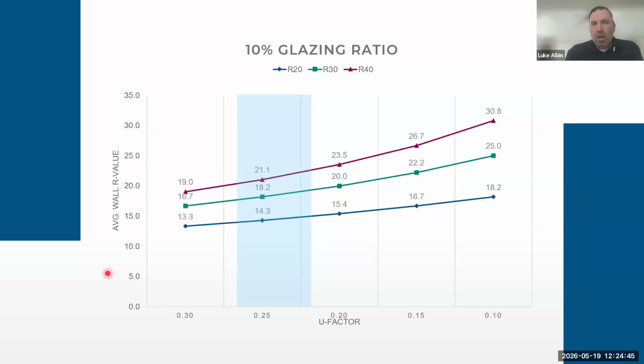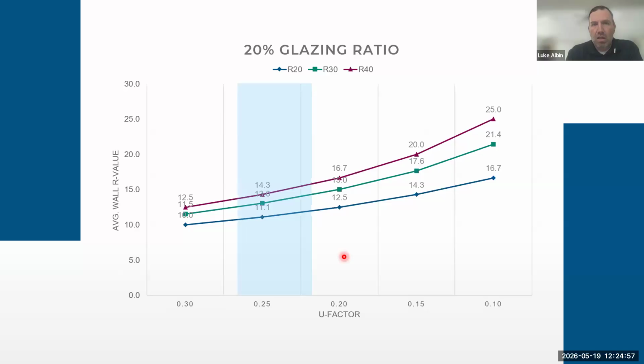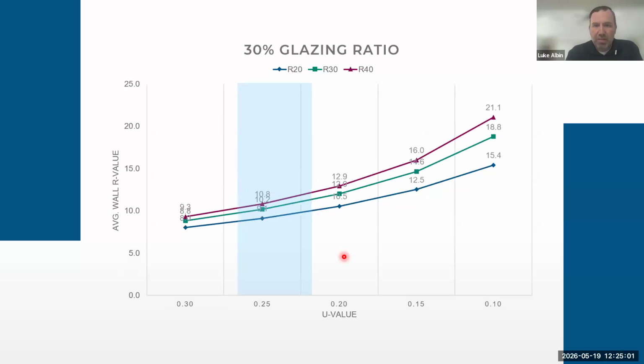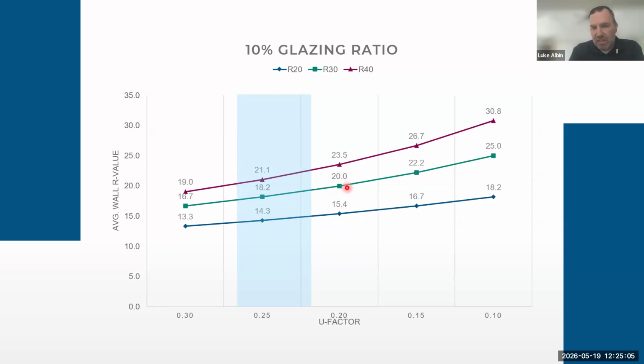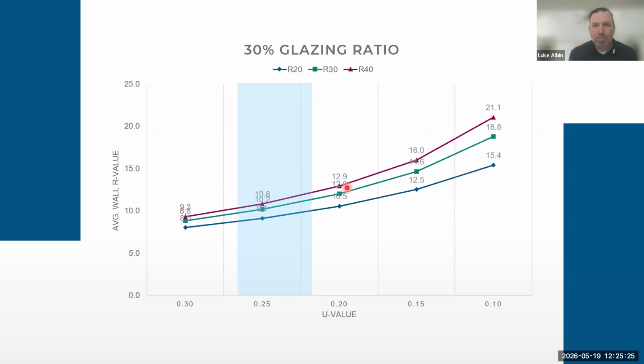But as you increase, I'd like you to pay attention to this area here, between the 0.20 and the 0.15. As we move up from 10% to 20% to 30% glazing ratio, and as I back off here a little bit, you can really see where the windows are getting closer to the wall's R value. So you really have more of an exponential benefit to using higher performing windows to get closer to the walls. So as you see here, 20% and then 30%. This is where primarily high performance windows will start off, between this 0.20 and below, again because of the relationship with the wall itself.